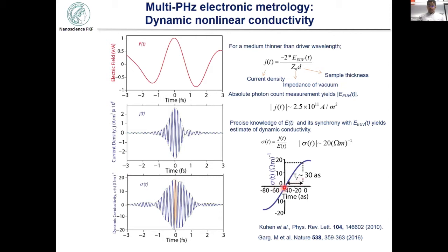In the beginning, when the laser pulse is not interacting with the system, it is almost insulating, and when you interact with the system, the dynamic conductivity increases by an enormous factor. This value over here is 18 orders of magnitude more than the static conductivity of SiO2. So basically it switches from an insulating state to a dynamic conducting state in a very small fraction of time.